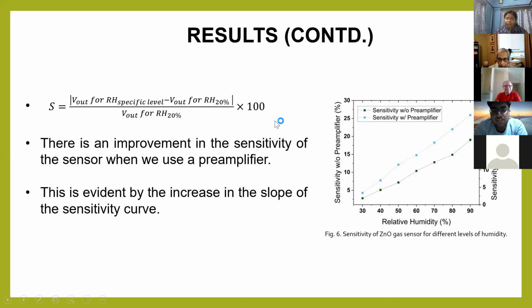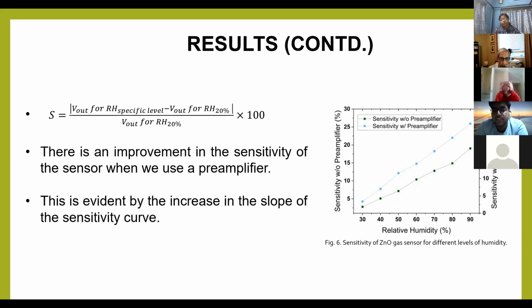Now, defining sensitivity at a particular relative humidity using the formula above, we have calculated the sensitivity for various relative humidity levels when the humidity sensor is employed with the designed preamplifier and when it is implemented discretely. We can observe that as relative humidity increases, the sensitivity of the gas sensor system increases almost linearly, which makes it an excellent feature for practical applications. There is also an improvement in the sensitivity of the sensor when we use a preamplifier. This is evident by the increase in the slope of this sensitivity curve when recorded with the preamplifier.